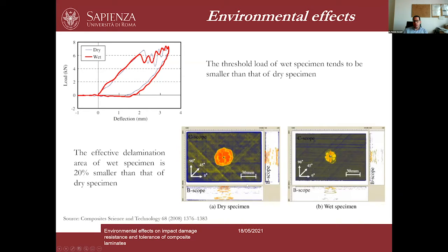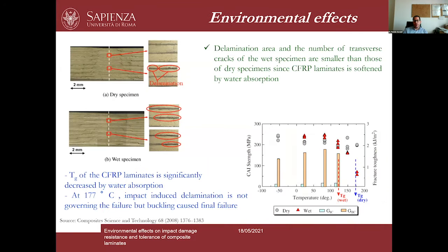So here you see, for example, a comparison of the delaminated area obtained by ultrasonic C-scans. And you can see that the delaminated area for the wet specimen was smaller than the delaminated area for the dry specimen. And this is basically related to the fact that the composite material became much more compliant. So it was, we can say, softened by water absorption. And this is related to the fact that the water can, in this specific case, significantly reduce the glass transition temperature of the epoxy matrix.